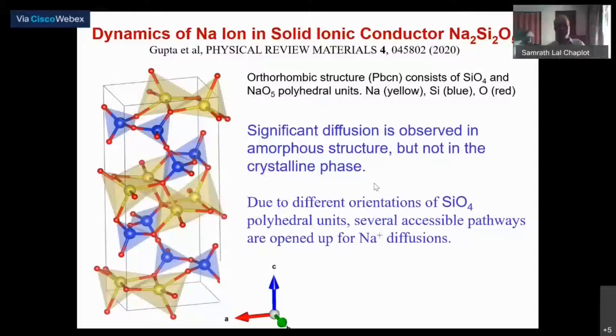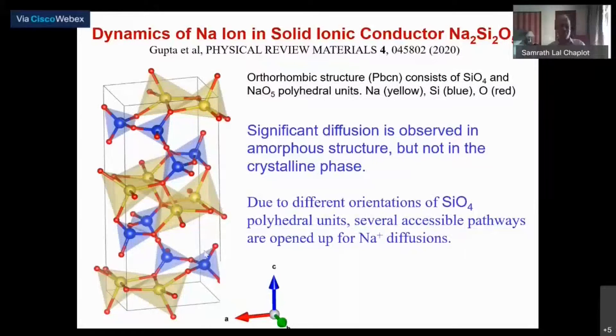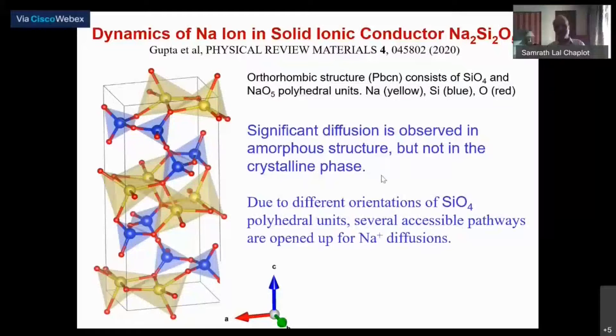Diffusion is actually observed in an amorphous silicate, not in the crystalline phase. The standard procedure is to start with the crystal structure, simulate up to very high temperature beyond the melting point so that atoms leave the lattice sites and you have a liquid-like structure, then rapidly cool — deep freeze it with a reasonable cooling rate — so that you cool it down to very low temperature and get an amorphous structure.